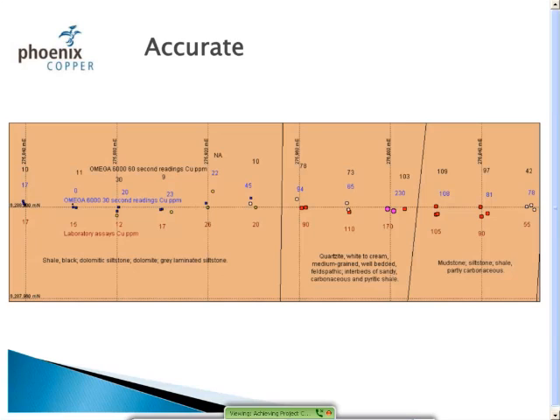This was an orientation exercise carried out by Phoenix Copper. What this data told them was that the XRF produced data that generally contoured in the same broad categories as the lab data. It showed them that 30-second reading times was sufficient for them to achieve the accuracy they deemed acceptable. This sort of orientation work is recommended for each XRF owner.